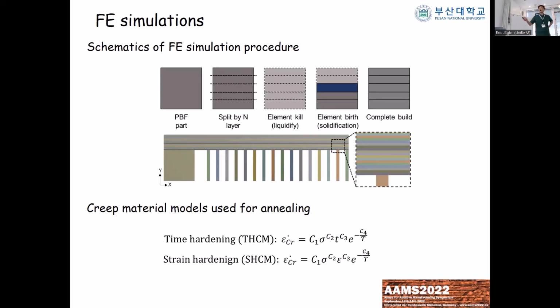So that is kind of the replication of the process, but we average or consider the material as being deposited one layer by one layer, and then it's shrinking again and again, something like that. So this is not special, it's already published research in the literature, but what was special was that to consider the annealing process, we have used creep material